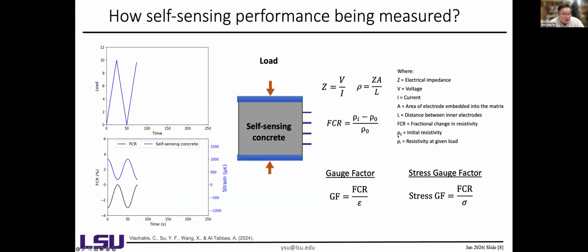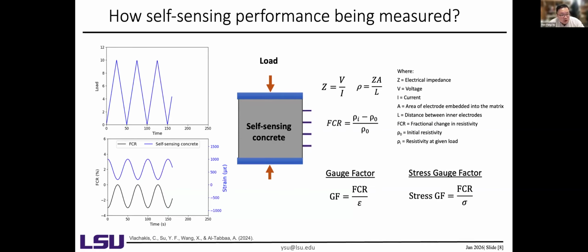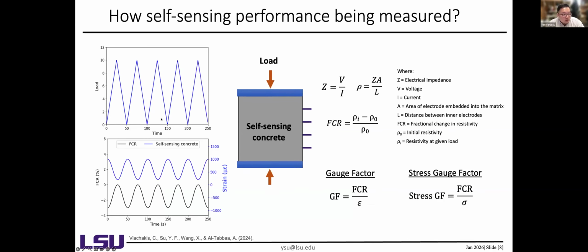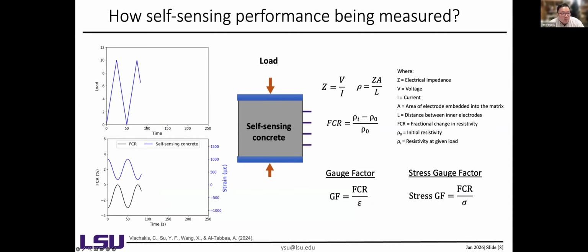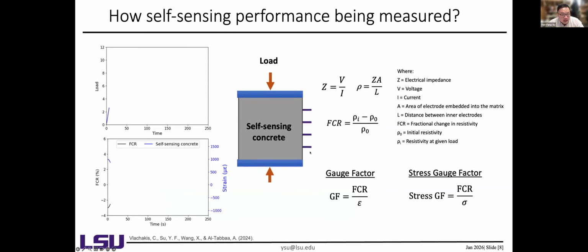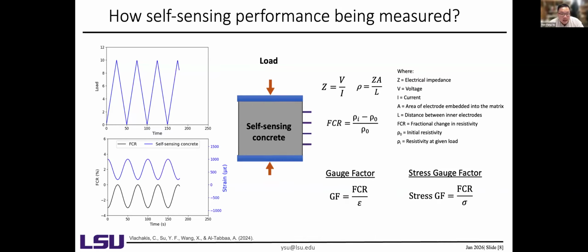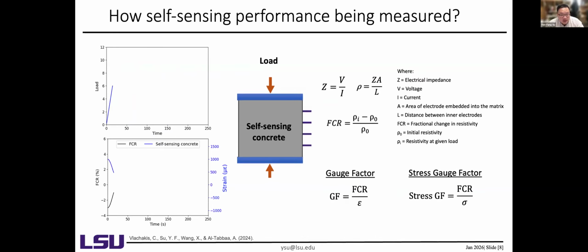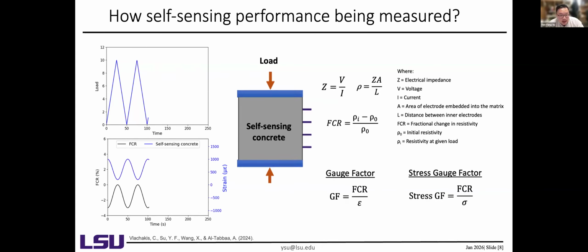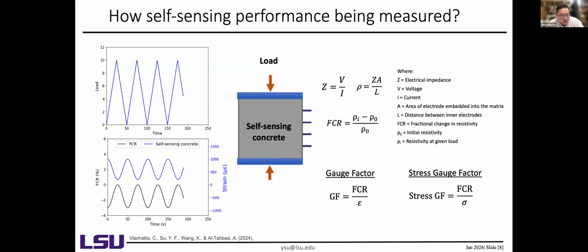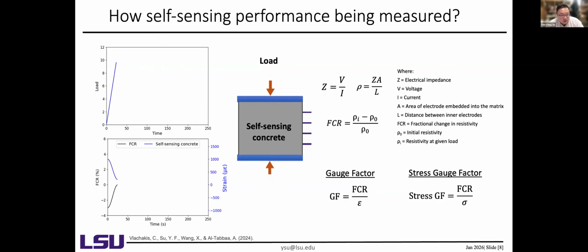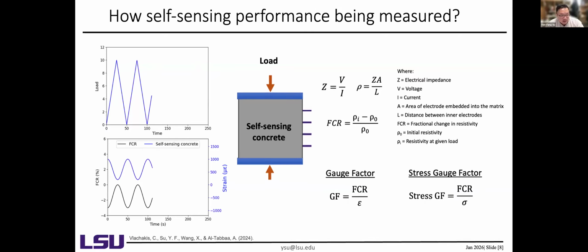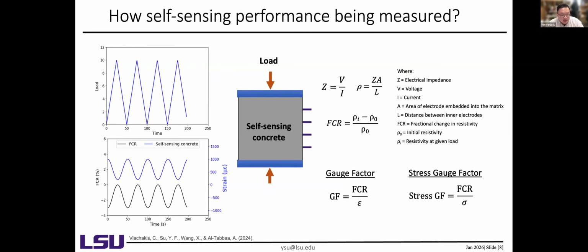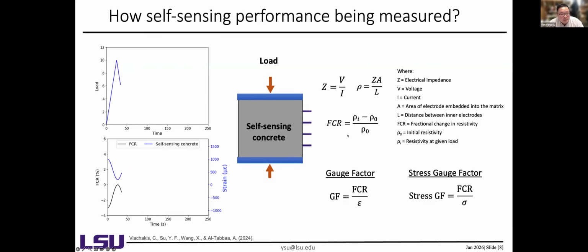So how can self-sensing performance be measured? Here I give you the animation we produced. If we apply the load to the material, we can measure the electrical signal by shooting the current into the material and obtaining the reflected impedance, and convert that to the fractional change in the resistivity. Then we further use this to calculate the strain gauge factor to compare with the strength or the deflection. So it's basically like a strain gauge, but it's built into the material itself.